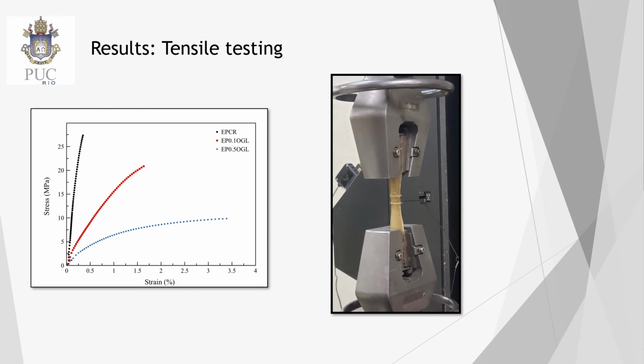So it's possible to see the brittle behavior of the neat resin here in the results of the tensile testing. So the EPCR without graphene, elongation is about 0.35%. The sample which has 0.1% of graphene followed the semi-brittle behavior closely, with a slight change in the curve. So the elongation has increased to 1.6%.